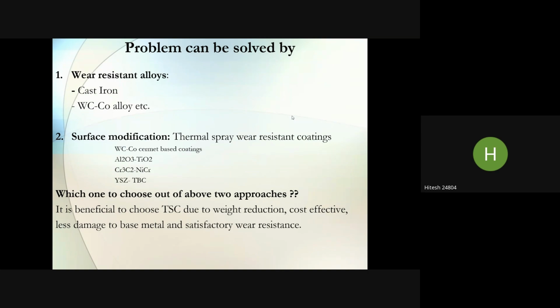Similarly, if you want to join two parts together by using some means of additive manufacturing, then you can use some pre or post treatments on the surface of the two parts which you want to join. Laser texturing is one of them. Then micro drilling is one of them, where we produce grooves intentionally to release the stresses in the component or in the part of a machine or machine tool, right? Similarly, extended versions of materials are available, but these are well-known materials. Here we cannot alter the composition of the materials. These are patented materials which can be used in the application. Like the second material which I mentioned, WC-Co, tungsten carbide cobalt.